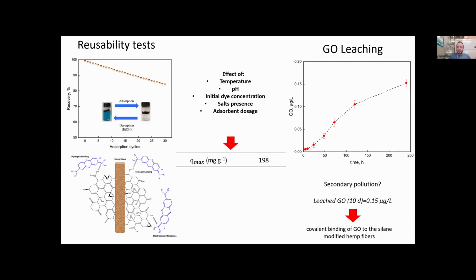Then several process parameters were changed to evaluate deeply the adsorption performances of this adsorbent, such as pH, temperature, concentration, salt presence, and adsorbent dosage. But I would like to focus on the reusability test. As you can see, after 30 cycles of adsorption-desorption, the loss is about 15%. So this adsorbent is able to preserve its capacity in removing methylene blue from water effluents. And since there is a possibility of leaching, we studied the leaching phenomena, which can be ascribed to the desorption of graphene oxide macro and nanoparticles from the surface of hemp fibers.